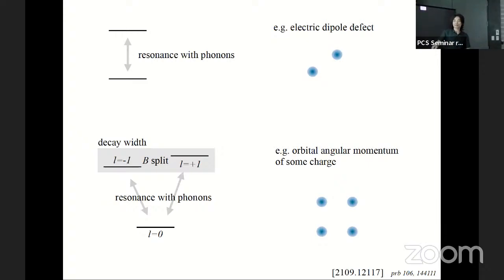So for resonance skew scattering, you can consider, for example, LCO has a C4 lattice symmetry. So we can consider some defect where some charge center, for example, can be at one of the four positions, not very well aligned with the lattice, but there are four positions that are equally likely. Okay, and then at these four positions, it can have an angular momentum 0, plus or minus 1, or 2. And angular momentum is well defined mod 4.